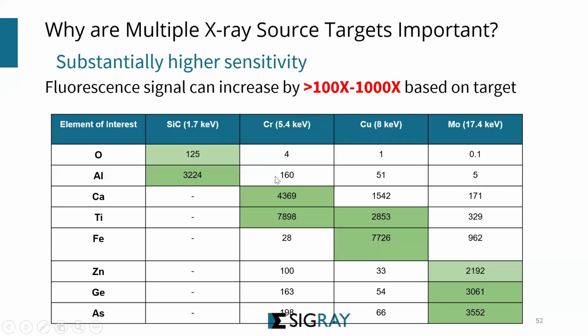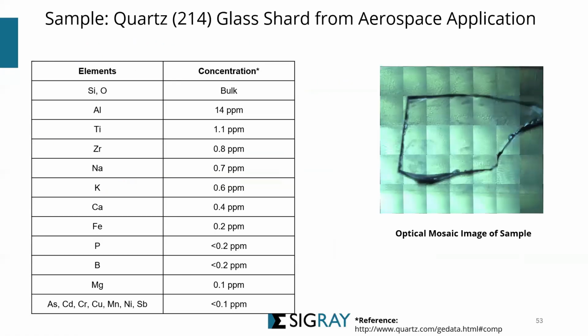What if you now go to chromium? Now you have jumped up to maybe 30 times better than your molybdenum. What happens if you now shift to your silicon? You find that you get a sharp increase of up to 644 times more. So in other words, you will be able to increase detection level dramatically without having to change other hardware or software or algorithm. That's as simple as that. That's the reason why it's so powerful in the synchrotron, and you can do that in the laboratory right now.